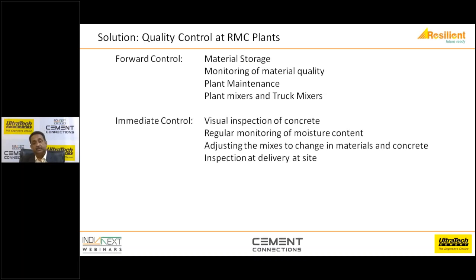Immediate control is when you actually do the controls at the time of batching. So the batcher should always visually inspect the concrete before it goes. For a trained batcher's eyes, he can make out whether the concrete is cohesive or the concrete has got lower slump or a higher slump. There are ammeters which are installed inside the mixers, which through the resistance of concrete can be correlated to the slump. Regular monitoring of the moisture content is another key area.